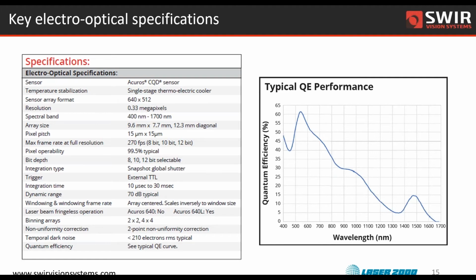Here's a little more detail on some of the specifications of the performance. Here on the right is a quantum efficiency curve, and it really gets to that. I think it shows the broadband response, we see 400 out to 1650, a little bit at 1700 nanometers, but also shows that the quantum efficiency in that red end of the spectrum is indeed lower than you would find in InGaAs systems. So InGaAs is up around 70 or 80% quantum efficiency. We're down around 10-15% quantum efficiency. And just to get right out in front of that, what that does mean is that InGaAs is ultimately more sensitive. So for really low light photon starved applications, these image sensors will struggle.